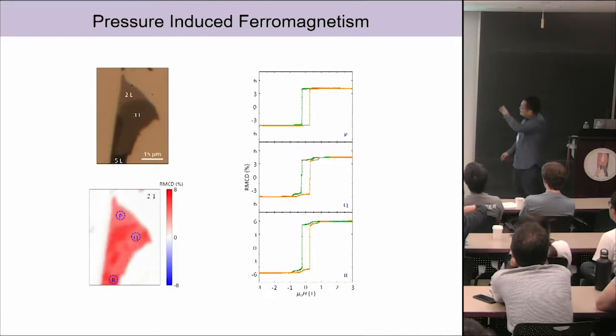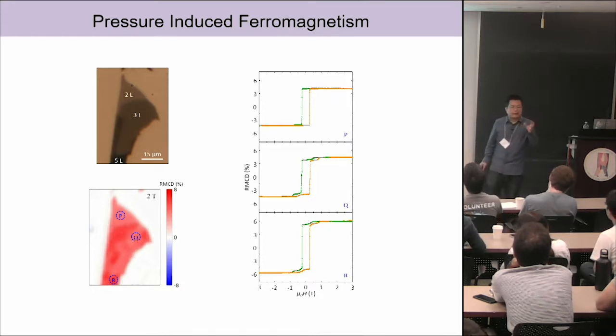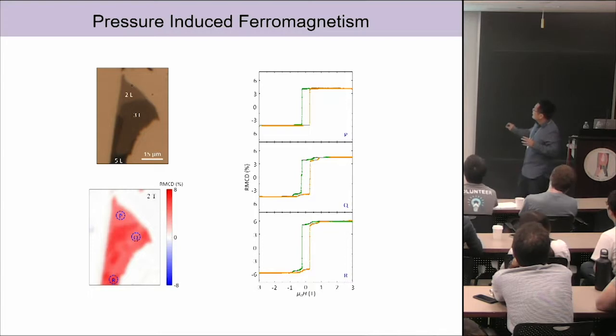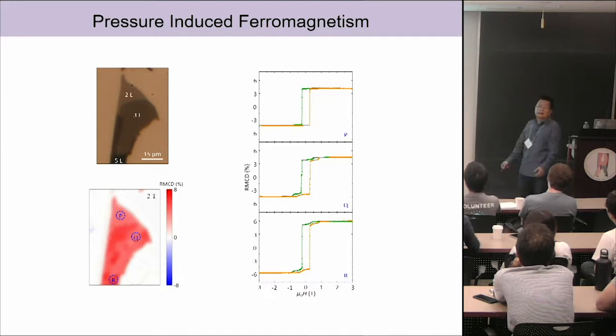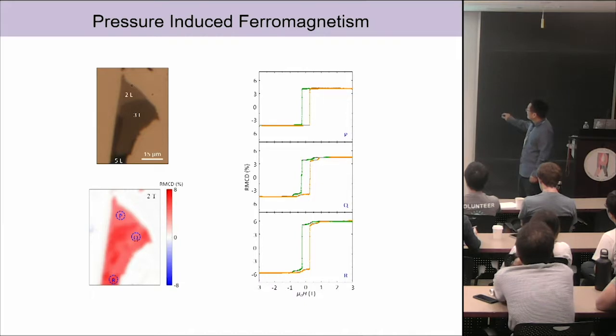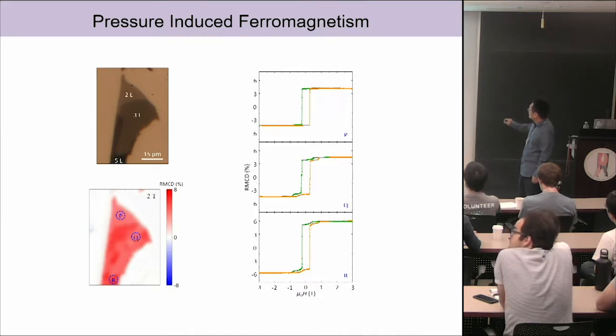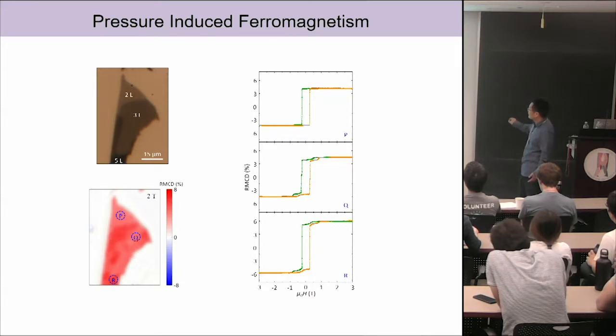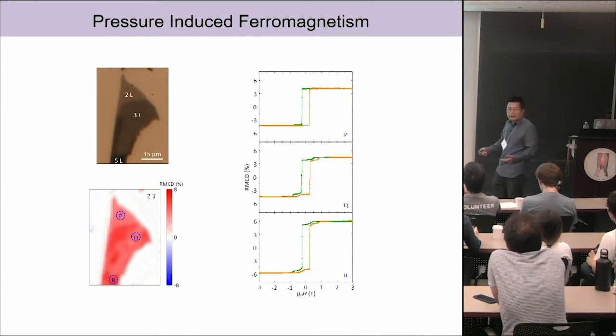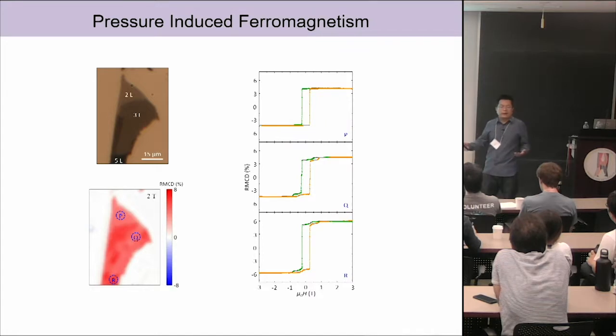And lastly, the example I want to show you is, well, this process is actually a little bit random right now. We cannot control it. For example, here's another sample we measured where it has 2 layers, 3 layers, 5 layers, and we just apply pressure, then we take it out from the pressure cell, and we do MOKE measurements. This is just 3 particular spots I chose. So all we see is a hysteresis curve. So it means that in this particular case, we turned the whole sample into ferromagnetic states. Okay.